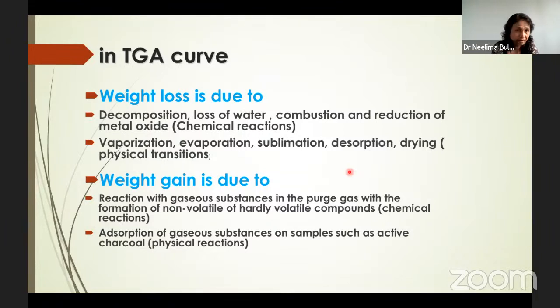You get weight loss in TGA curves with decomposition, loss of water, combustion, reduction of metal oxides, vaporization, evaporation, sublimation, desorption, and many physical transitions like drying. If water gets evaporated, you get weight loss. If you get weight gain, it must be a wrong selection of your purging material, because some materials can react with your purging material and form oxides, because of which you can get a weight gain, or from reactions of the gaseous substances which are evolving with the purge gas. Your sample loader is continuously purging with your inert atmosphere or atmosphere of interest, and if your purge gas interacts with the sample, then you get a weight gain in your TGA curve. And an expert can easily identify that.